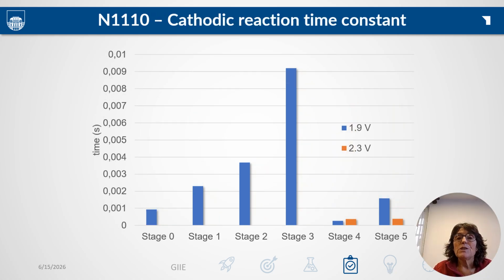The cathodic charge transfer time constant grows during degradation and then drops sharply after regeneration, almost to pristine values. This is the kinetic recovery I mentioned. The drop is most marked precisely at the cathode, compatible with the removal of reduced impurities by the acid treatment.